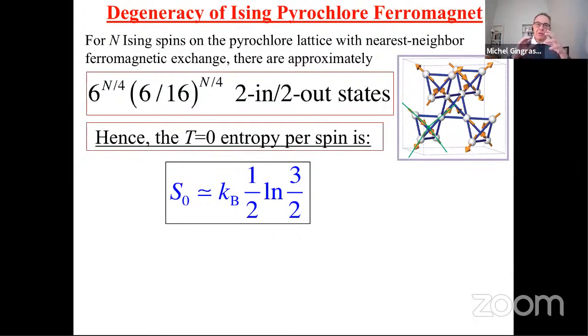They are connected to each other. And so the bridging tetrahedron that intervenes between the surrounding tetrahedra must also obey the 2-in/2-out rule. The hand-waving estimate of how many of the 16 states the bridging tetrahedra can satisfy is 6/16. This is an estimate. It is an infinite series in calculating this number of ground states, which was done more recently by Rajiv Singh and Jan Oitmaa. But the point is that there is an extensive number of ground states that satisfy the 2-in/2-out rule. So it's really a 2-coloring problem, in a sense a simpler version than the Kagome one. On each tetrahedron, I must have 2 sites that are black and 2 sites that are white, essentially. And this is the number of states.